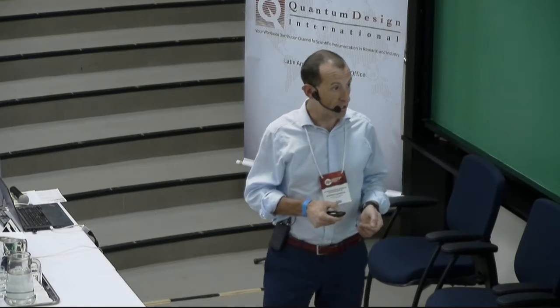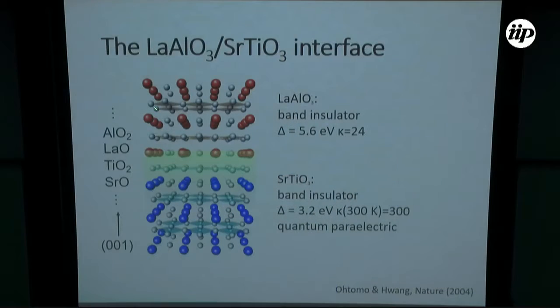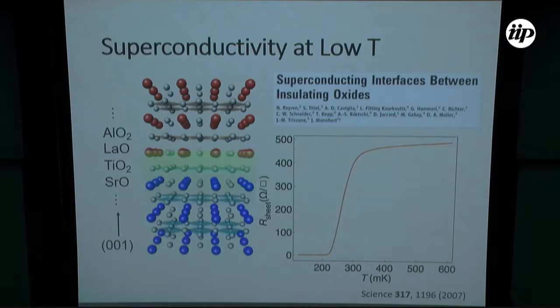So this work has been done mainly by Alexandre Fête at the University of Geneva, and as I said, it's a transport study of the lanthanum aluminate strontium titanate interface. As you may know, this system hosts a 2-dimensional electron system that sits on the strontium titanate side of the interface, and at low temperature it undergoes a superconducting transition. Now, what is interesting for us is that this electron gas that self-confines on the strontium titanate side is sandwiched between 2 high dielectric materials, lanthanum aluminate on one side, and strontium titanate on the other side.